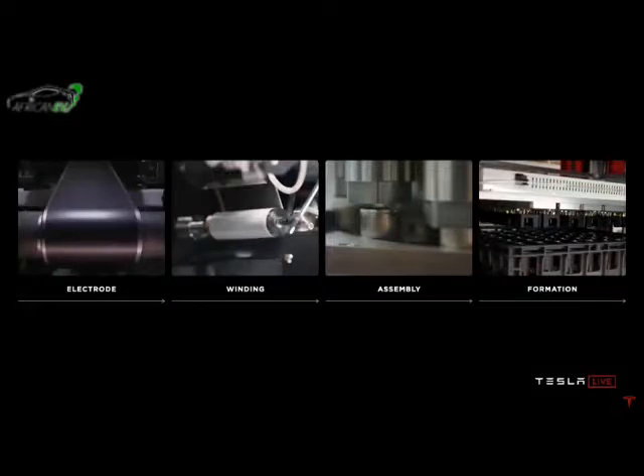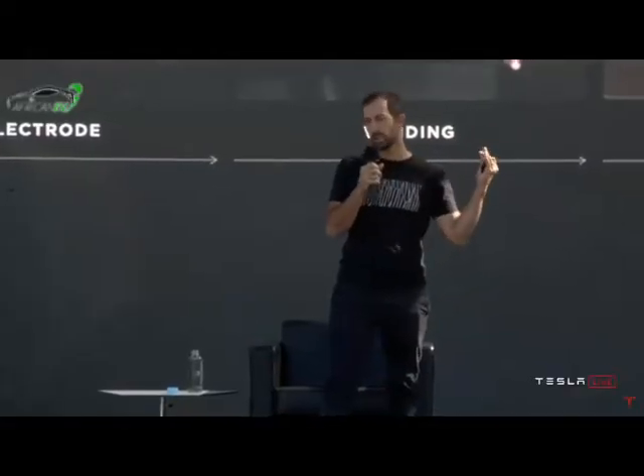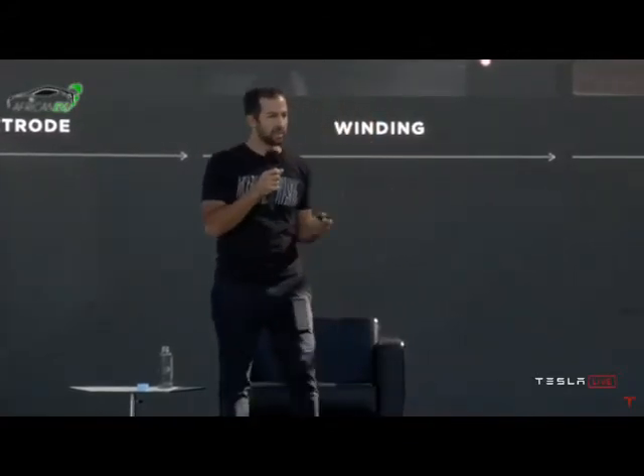Let's talk a little bit about what's in a cell factory. First, there's an electrode process where the active materials are coated into films onto foils. Then those coated foils are wound in the winding process we just talked about, where if you do have tabs, you have to start and stop a lot. Then the jelly roll is assembled into the can, sealed, filled with electrolyte, and then sent to formation, where the cell is charged for the first time, where the electrochemistry is set and the quality of the cell is verified. And we set out at every step of this process to take that inspiration we just showed and think about how we make those processes fundamentally better and more scalable.